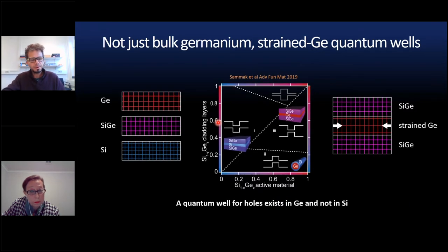So what we are working on is not bulk germanium, but actually strained germanium quantum wells. Germanium and silicon have different lattice parameters, but there's a nice alloy, which is silicon germanium, which can take a lattice parameter in between the two. So by working with silicon germanium heterostructures, you can tune the band structure of these materials, for example, to confine holes into this quantum well. So this is a structure we will look at.